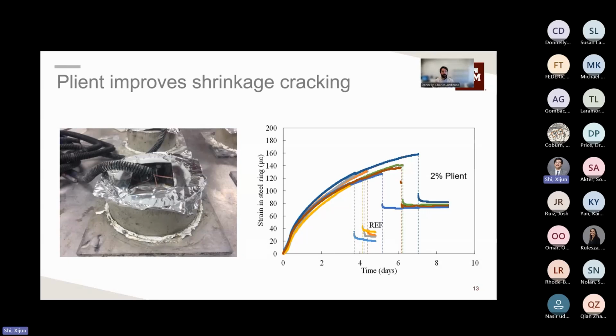So a series of ring tests were performed. Essentially what a ring test is: inside this test setup here, there's a central steel ring, and an outer ring is placed with a gap between the two rings. The Plient concrete is poured into the gap between the rings and allowed to initially set, at which point the outer ring is removed. There's a series of strain gauges on the inner ring, which measure strain development as the concrete is starting to cure and set.